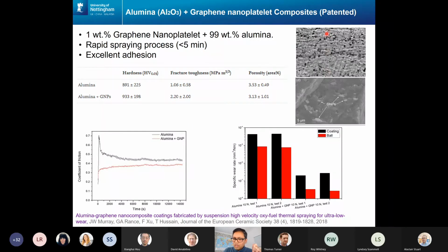That's the cross section of the structure, and all of these dark bits are the reinforced material. And that's a fracture surface. When we have fractured it, we can start seeing those graphene nanoplatelets, or GNPs, embedded in here. One of the challenges of ceramics is fracture toughness. Ceramics are brittle. But by adding the graphene nanoplatelets here, we can increase the fracture toughness quite significantly.